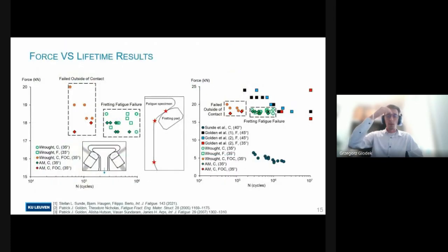Now, moving on to the overview of the experimental results, the lifetimes of tested samples are shown here on the figure on the left. Now, if we focus on this region, we can see that the performance of the additively manufactured Ti-64 is somewhat worse than the wrought material, but this comparison is made a bit difficult due to large scatter in the wrought data and also a number of samples that failed outside of contact. So for the wrought material, it was mainly a failure at the curved edge. For the additively manufactured material, the failure also occurred at the neck here, or the transition zones, but I will talk about it more in a second.